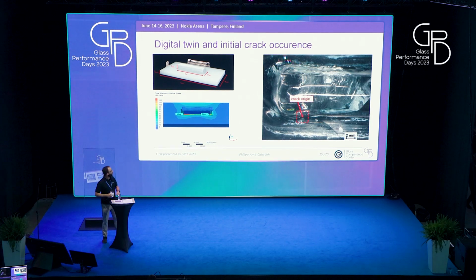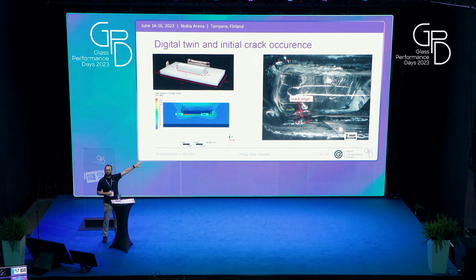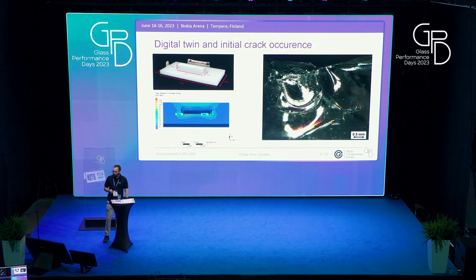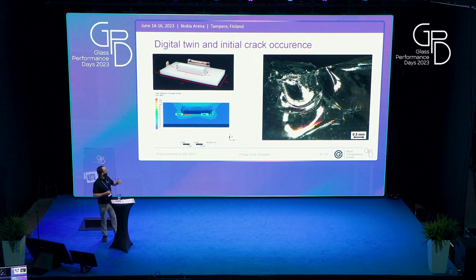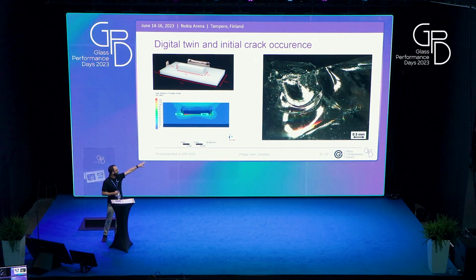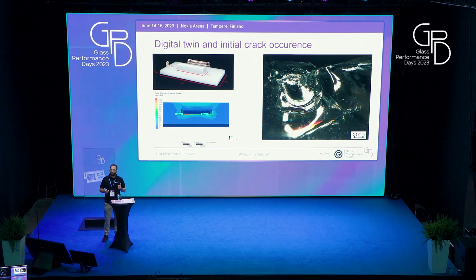On the right side, it's difficult to see. It's a top view of the AM glass component where the crack should occur and did occur. Here you can see the section view, where we try to figure out the fracture mirror. You can see the lancet cracks. So we know where the crack occurred. Now the question is, how does the crack develop?